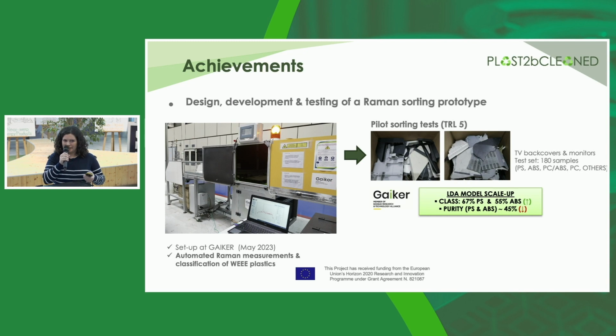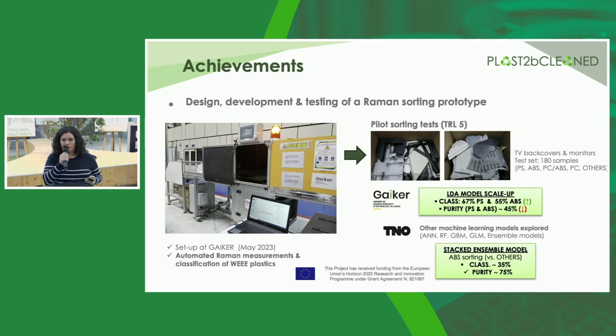In this moment, we collaborated with a TNO expert at data analysis, and they have also explored other machine learning models, artificial neural networks, random forest or ensemble models. And with the pilot RAMAN spectral data, they have trained a model that could sort ABS with a purity around 75%. So this result was closer to the result that we have obtained at lab scale.